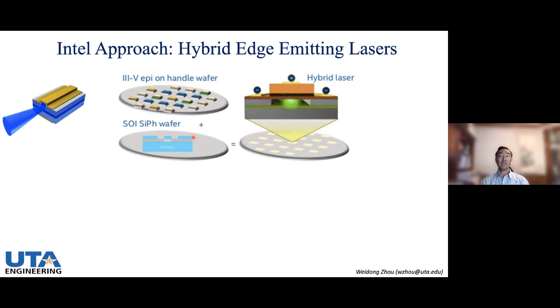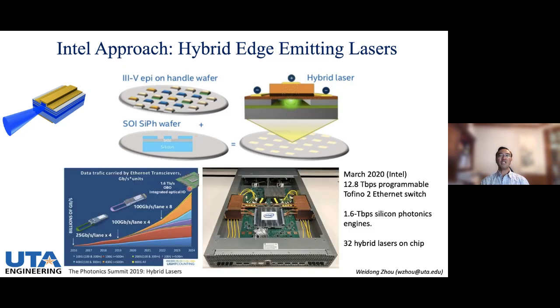So it has been very successful and addressed many issues in terms of reliability and the process. And they were also able to successfully integrate it into their transceivers for data centers, and also into this kind of humongous switching capacity Ethernet switch, with the silicon photonics and the hybrid laser inside here. They have been able to integrate. So it has been very, very successful already.